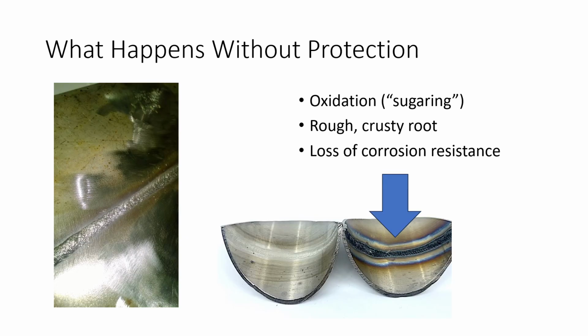So what happens without protection? Oxidation. On the inner root, we get a thing called sugaring. This is a rough, crusty, nasty looking root. And what it does is it means we've lost corrosion resistance. Whatever fluid is on the inside of that pipe is going to chew through that oxidized, sugared root and start wrecking the metal. So that's a bad thing. We do not want that to happen.